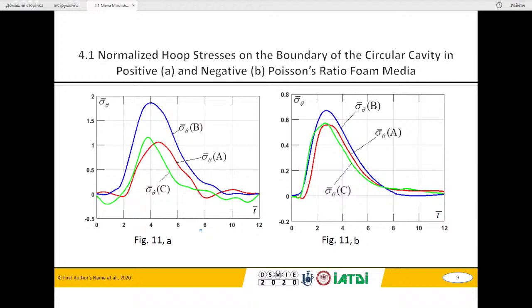Comparing the numerical results shows that the maximum values of normalized hoop stresses at the boundary of the cavity are 2.4 times smaller in material with negative Poisson ratio than in materials with positive Poisson ratio. Besides, the distribution of hoop stresses along the boundary of the cavity is substantially different for materials with negative Poisson ratio. Next slide, please.